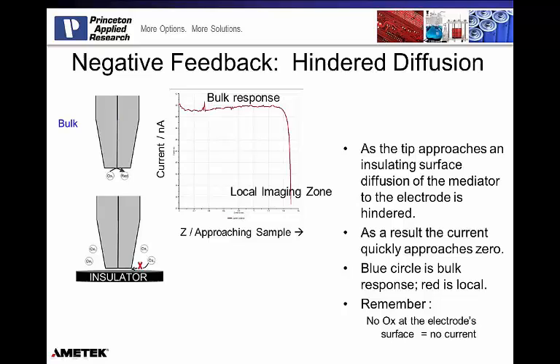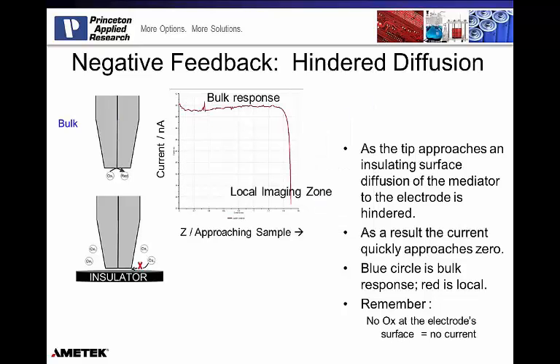The probe is held at a constant voltage, but because the position is changing and the mechanics of the cell are different, I'm no longer allowing access of ox to that platinum wire. Without ox at the platinum wire, no electrochemistry is happening. No electrochemistry happens, the current turns off. And we see that bulk response come here in the bulk state and then go down dramatically. Then we're going to stop that response before we get to zero. Theoretically, you would get to zero at the sample surface, but we want to stop a little earlier to account for any kind of topography effects or any kind of tilt in the probe or the sample itself.